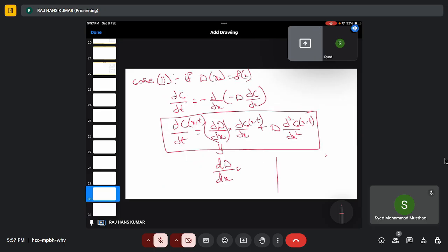So there we apply J equals to minus M C dou mu by dou x, where mu is my chemical potential, where M is my mobility. So that is about the flux in terms of chemical potential. Now, that is all about today's session.